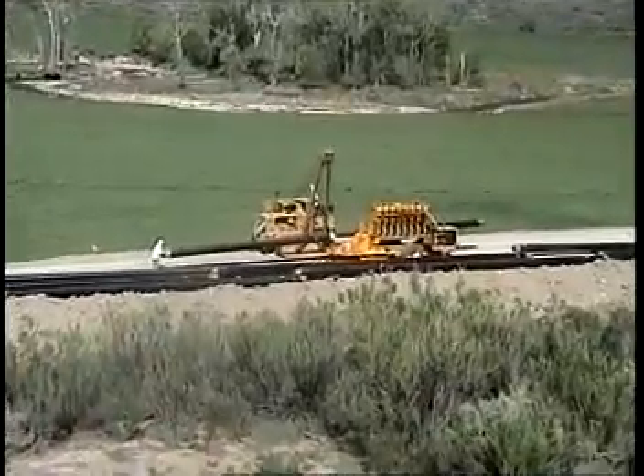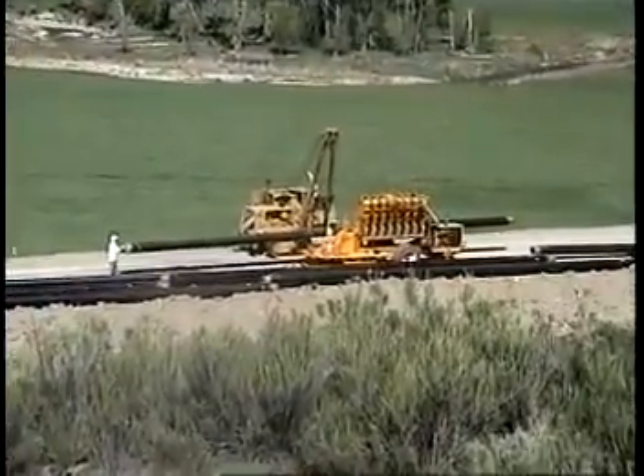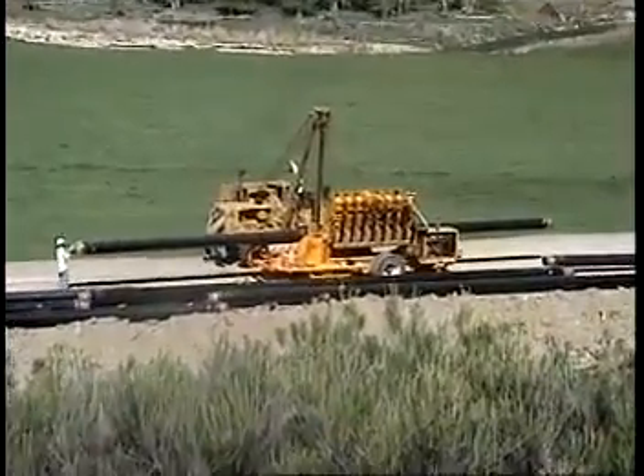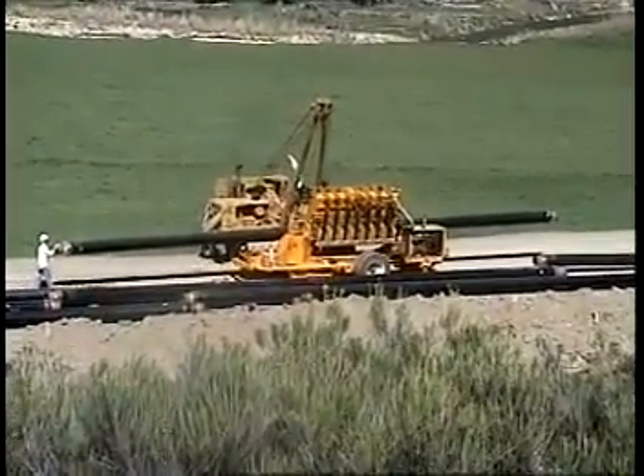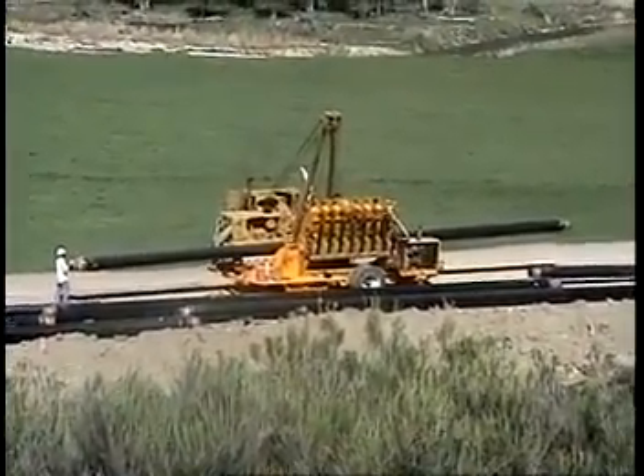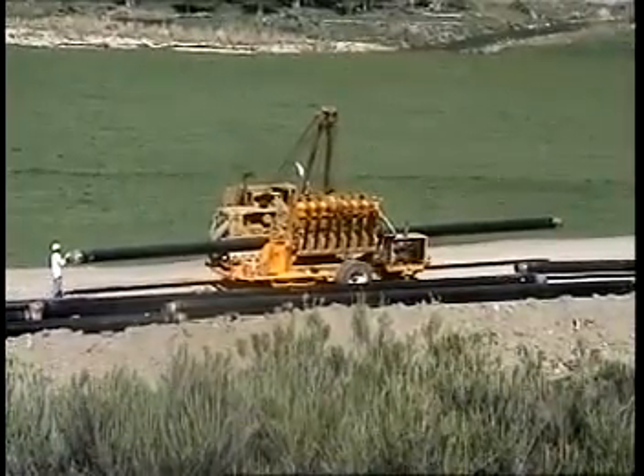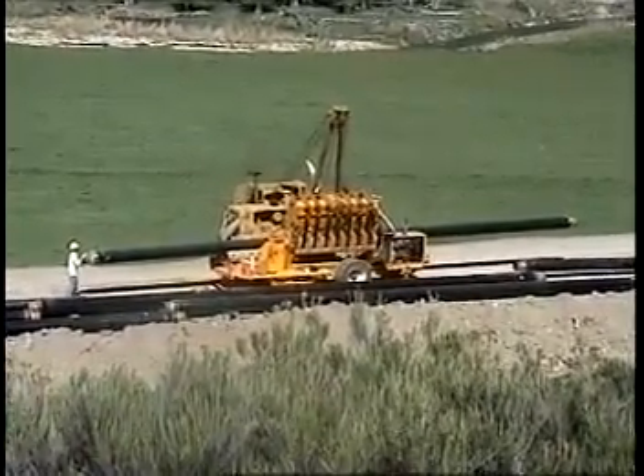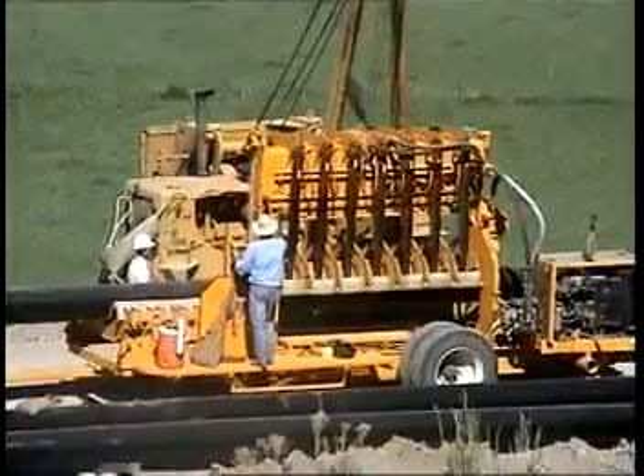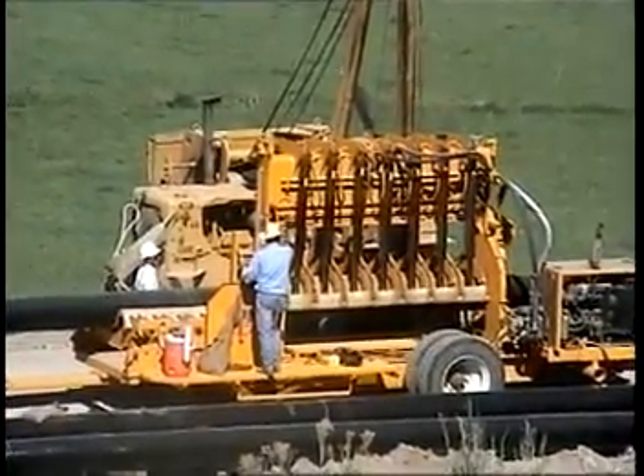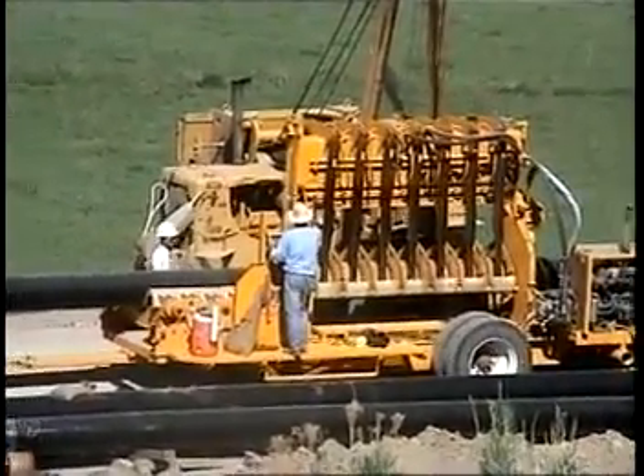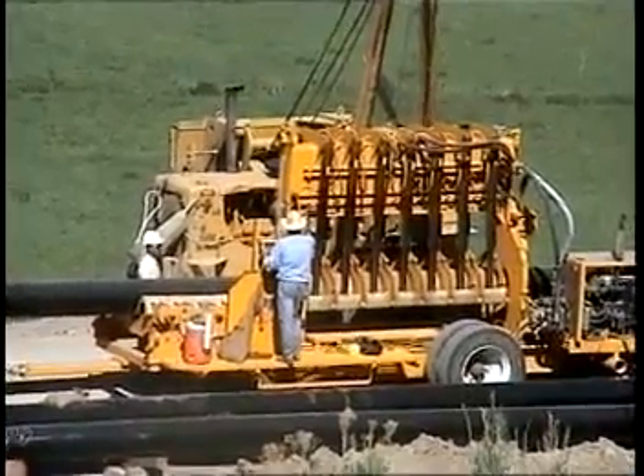A bending machine was used to bend the insulated and jacketed pipe. The compressive strength of the foam and the thickness of the jacket were controlled so that the bending machine would not damage them. The maximum angle that could be field bent was 1.5 degrees per foot. These bends were used to follow the contour of the ground and also to make gradual changes in direction.